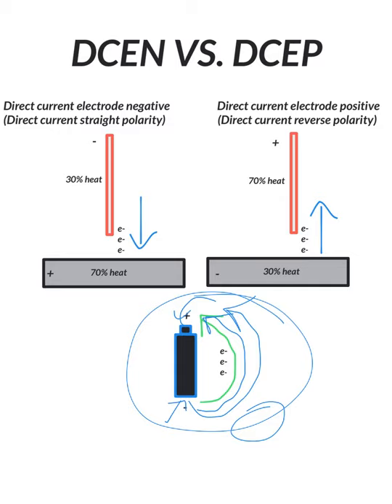The flashlight will turn on. We're going negative to positive. Here is a stick electrode I have right here. If we say it is direct current electrode negative, the electrode is negative. I put a little negative sign here. That means our base metal has to be positive. 70% of our heat will be here because our electrons are flowing from negative to positive. Wherever the electrons go is where the heat goes. This is also known as straight polarity, direct current straight polarity on older machines. So if you see DCSP, that's straight polarity, that's the same as negative.